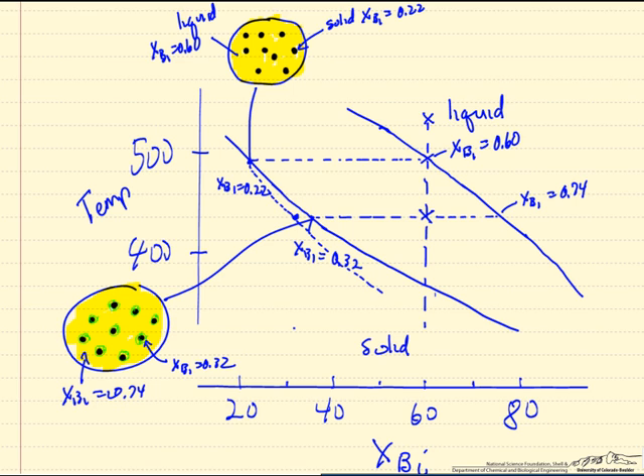This is just a schematic representation. When we get to this point, we have some overall average solid composition in equilibrium with this liquid. But unlike the equilibrium case, we have not formed all solid. In the equilibrium case, this would all be solid.